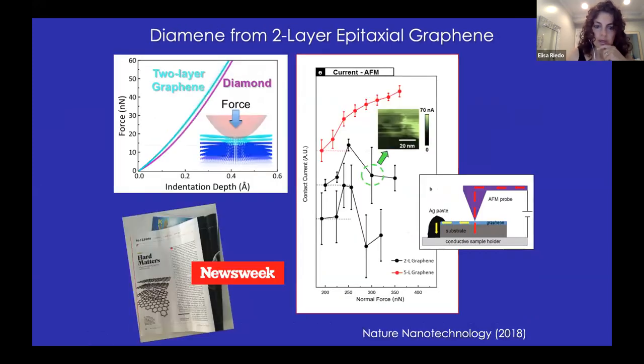So we are undergoing more and more studies about this very interesting phase transition, also in other systems like hexagonal boron nitride. We also started to run current AFM measurements to understand at what load you really see this phase transition, and we realized that the load is about 250 nanonewton. Based on all these studies, we also became more interested in the dissipation mechanism, and that is the second part of my seminar today.